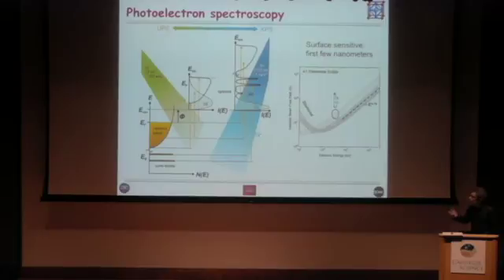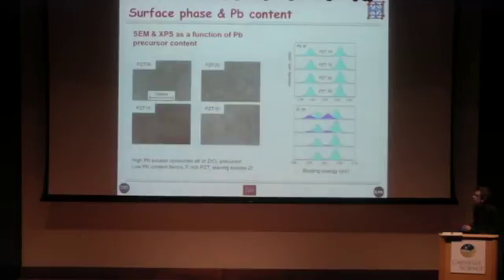Very important is that this is essentially a surface-sensitive technique. Here is the kinetic energy of the photoelectrons, and this is the inelastic mean-free path, the distance traveled before undergoing some kind of inelastic collision and therefore losing energy. And it's roughly a nanometer for typical electron energies. So we're looking essentially most of the time at the surface of our samples.